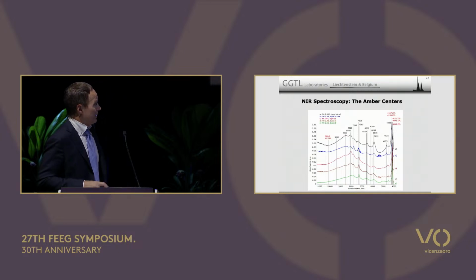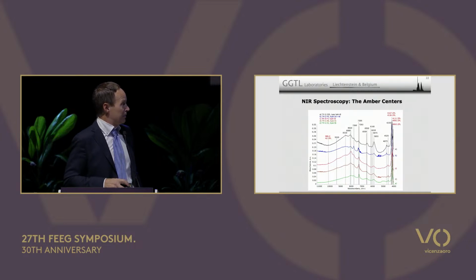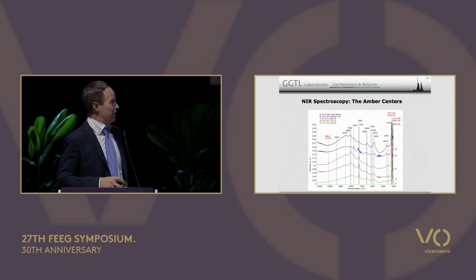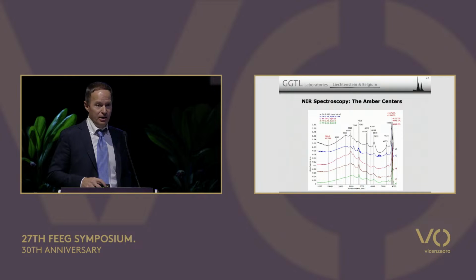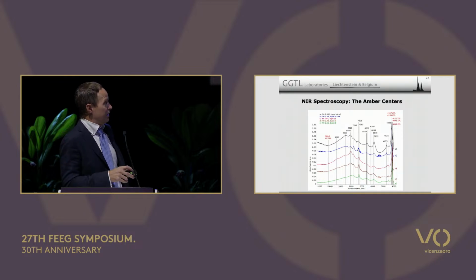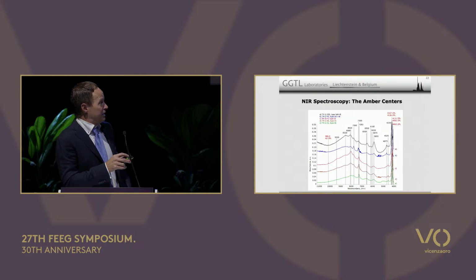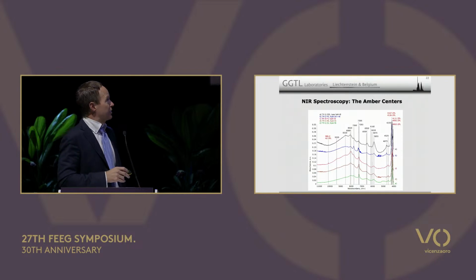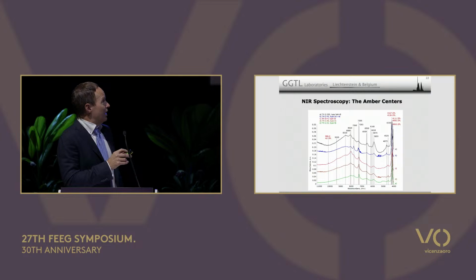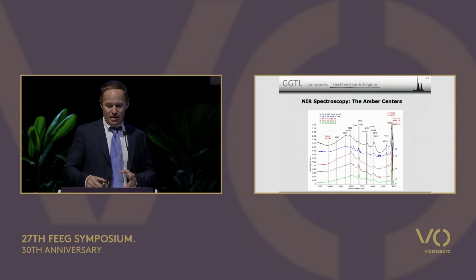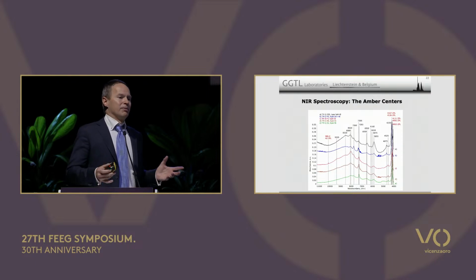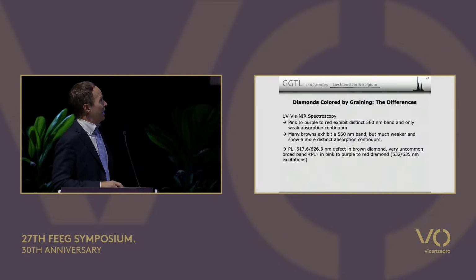Here, the near-infrared domain of some brown diamonds taken at low temperature. This has been taken with a special near-infrared spectrometer at liquid nitrogen temperature. And you can see that the amber center has a range of zero phonon lines and all these vibronic bands that range all the way to about 1200 nanometers. This is typical. The amber center in 1B stones is different than in 1A stones, but you can actually transform them via treatment, and that's part of our project here.